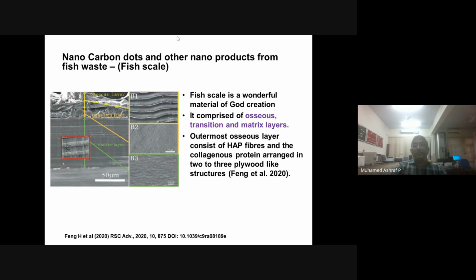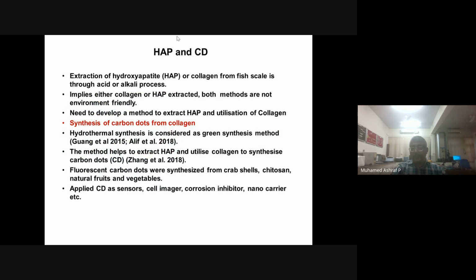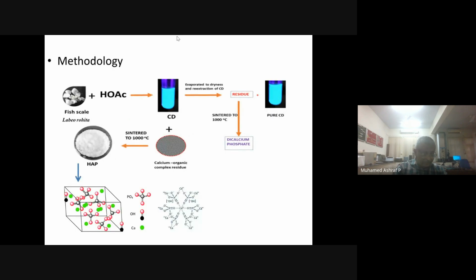And we know that if you extract collagen by chemical methods, you will lose hydroxyapatite. If you extract hydroxyapatite, the collagen will be lost. So we thought that we could convert this collagen to carbon dot, and then extract hydroxyapatite as a material. Based on this concept, we developed a small methodology where the fish scale was treated with a hydrothermal reaction, and we prepared carbon dot. We got a solution including carbon dot and hydroxyapatite. Hydroxyapatite came as a precipitate.